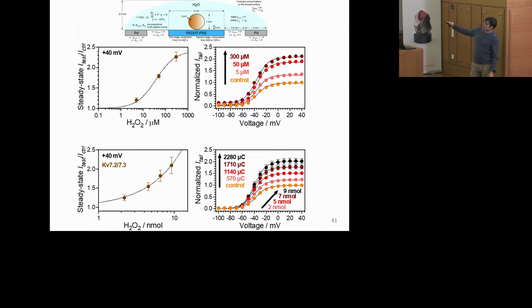Here is the perfusion curve. So we are perfusing peroxide in. It's a controlled experiment. We're perfusing peroxide in. We see the increase in potassium current. So we see potassium current going up, up, up, up, up. And in these curves, we're not adding peroxide. We're just running this pixel, running low-level DC current between PEDOT:PSS and palladium. And we see a very similar curve. We see this increase of potassium.